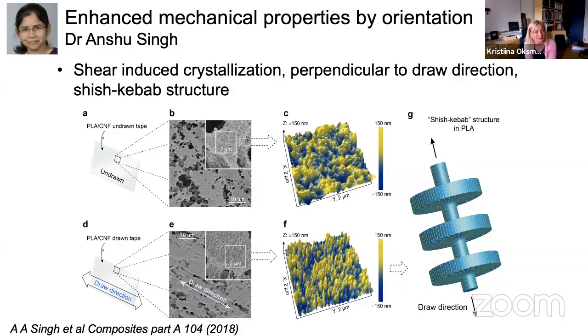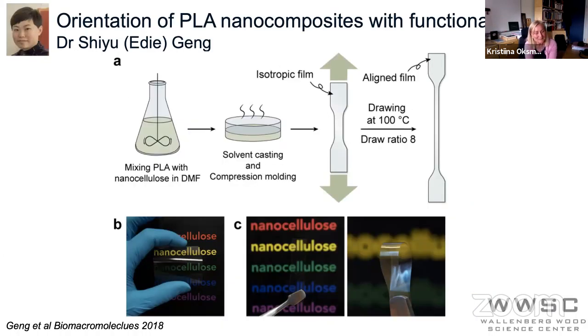And when we have a closer look at the structure, we etched out the amorphous PLA, and we can see this orientation, but we can also see that these crystals are growing perpendicular to the draw direction. It's this kind of shear induced crystallization, and it's forming this shish-kebab structure. It is very interesting. So that then led us to be even more interested in this orientation, and whether we could improve the properties of PLA with cellulose nanofibers without any plasticizer.